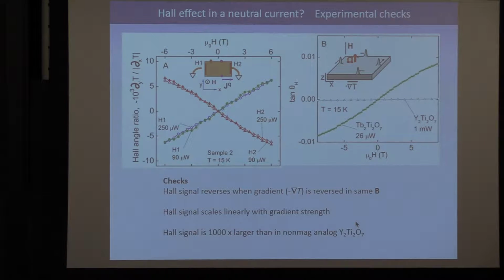And so if it's a thermal Hall effect, when you change the heat current direction, it should reverse in sign, right? And it does. So this is actually easier said than done, because unlike an electrical measurement where you simply go up to your current source and flip the sign, there's no way to flip the sign of a thermal current, right? You have to go in there and laboriously change the heater connections, and then so you initially heat this end, right? So the heat current flows to your right, and then you warm the system up, remove this gold wire, attach this one here, and then reverse the current, hopefully without changing the sample. And remarkably, you see the Hall signal reverses sign.